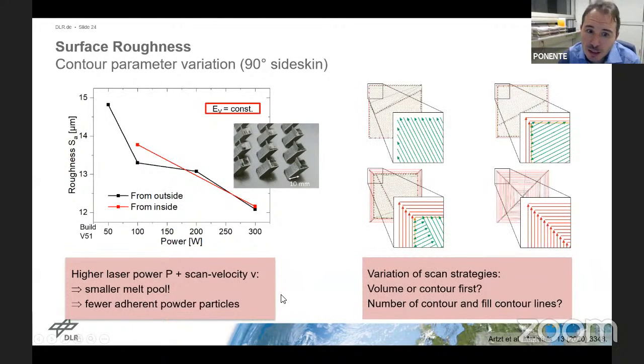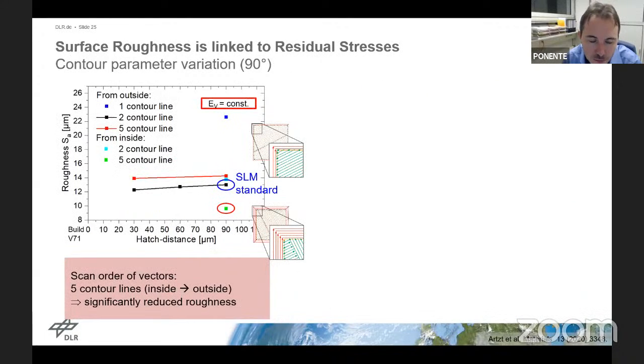Okay. So adjusting the laser parameters helps a bit, but what we found helps most is actually changing the scan strategy at the surfaces. So it's the question whether you only do bulk hatching, then it's only those green vectors, or you start putting contour lines and fill contour lines, different numbers of contour lines, 2 in this case, 5 in this case, and also with different scan order before or after the green bulk lines. That gives you a lot of space to optimize the surface quality. This is kind of shown here.